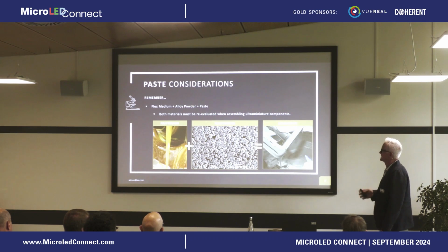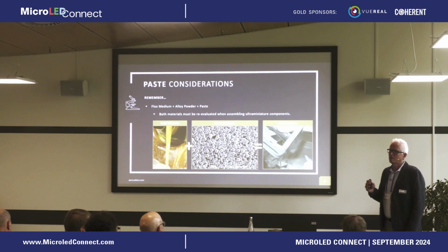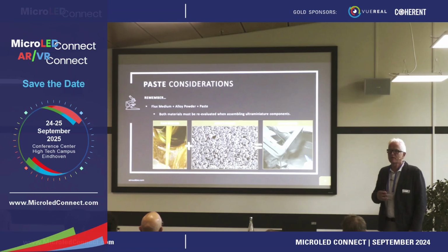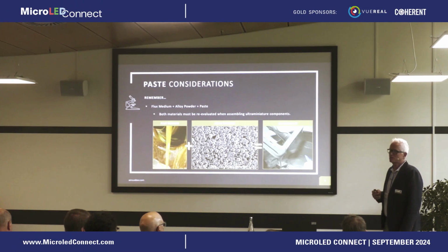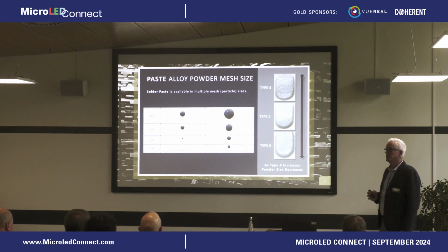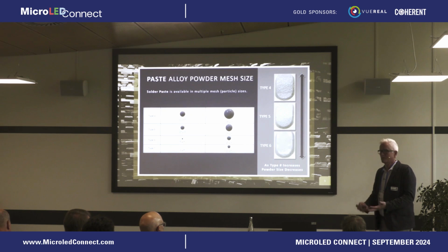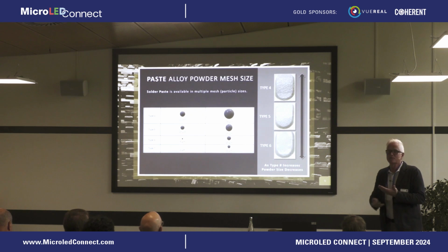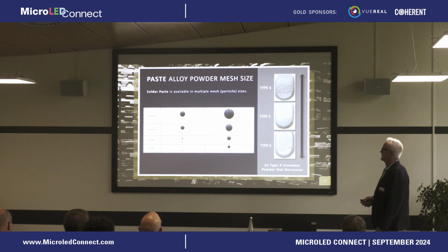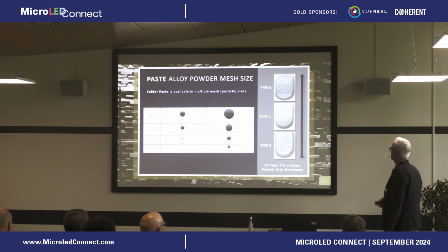And controlling the size of the spheres to blend the material has a lot to do with your success in whether or not you can print these very, very fine features in a traditional surface mount printing process. And a traditional surface mount printing process is a lot like silk screening a t-shirt. You have holes in the stencil where you want the material to transfer through it. It goes through the hole and it deposits itself on whatever's underneath. It's very precise and sophisticated in this application, but fundamentally that's what it is.